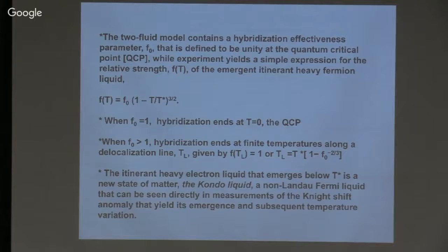What's the difference? How do you tell experimentally? Experimentally, if it's a weakly hybridizing system, you're always going to have local moments around. And they're going to lower their entropy by forming a Néel antiferromagnet. So you see antiferromagnetism. At the same time, conduction electrons are there, and they happily superconduct by exactly the same mechanism we proposed for the cuprates, namely an attractive interaction induced by their coupling to the quantum critical spin fluctuations.